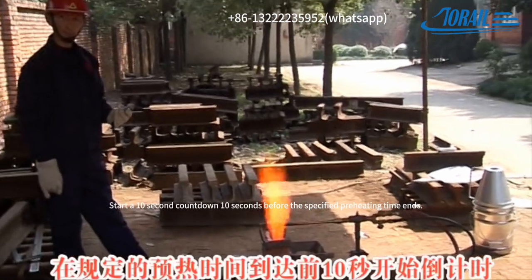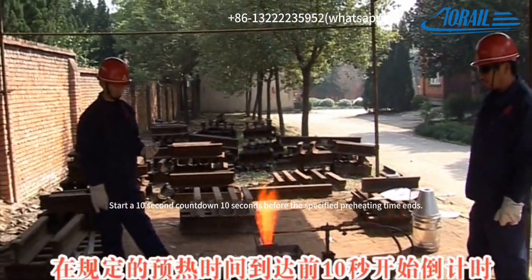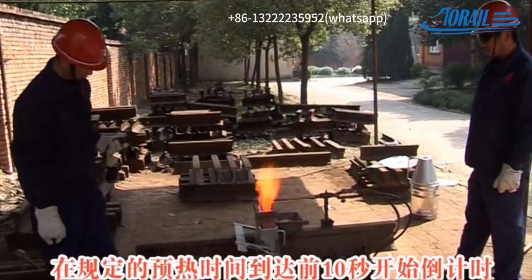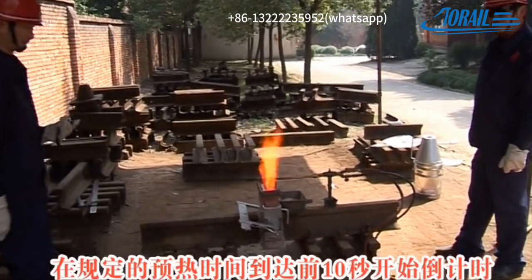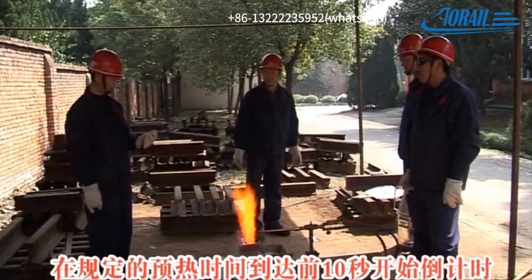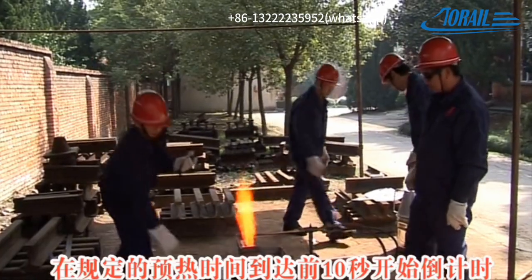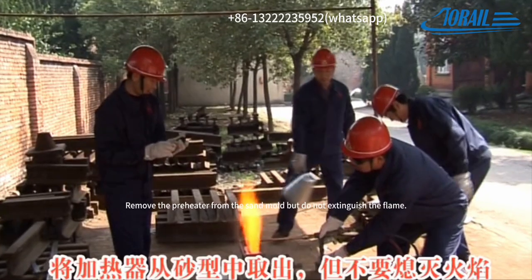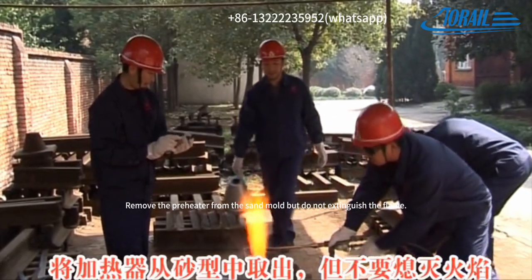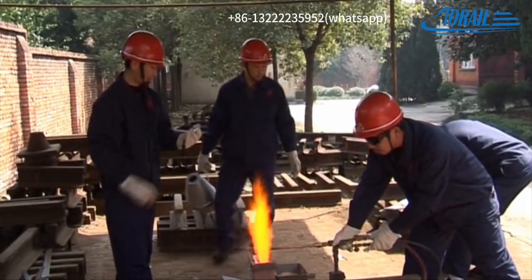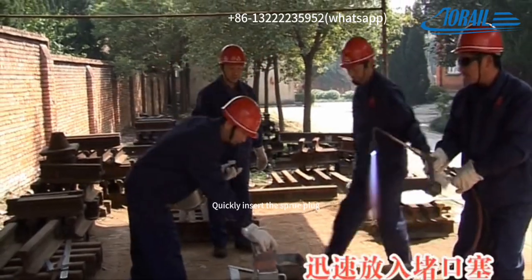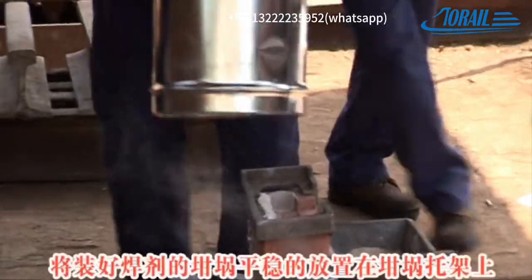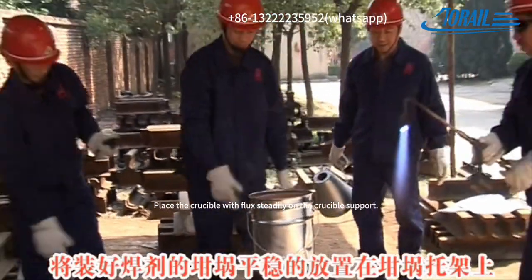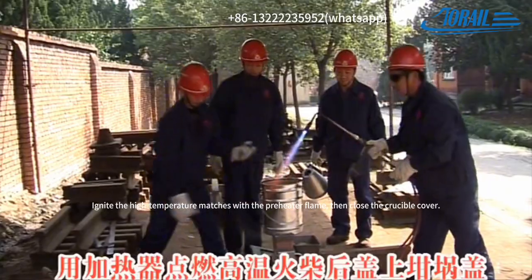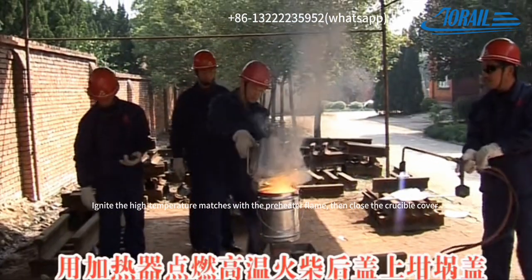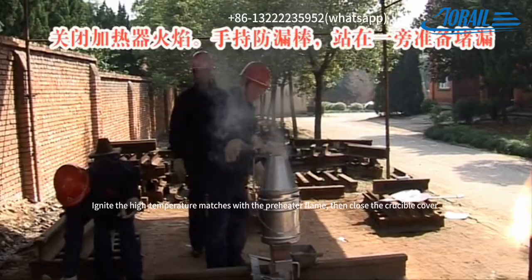Pouring. Start a 10-second countdown 10 seconds before the specified preheating time ends. Remove the preheater from the sand mold, but do not extinguish the flame. Quickly insert the sprue plug. Place the crucible with flux steadily on the crucible support. Ignite the high temperature matches with the preheater flame, then close the crucible cover.